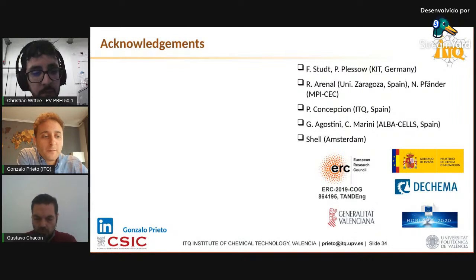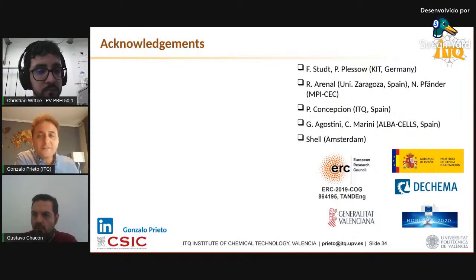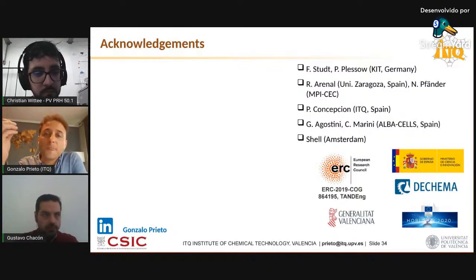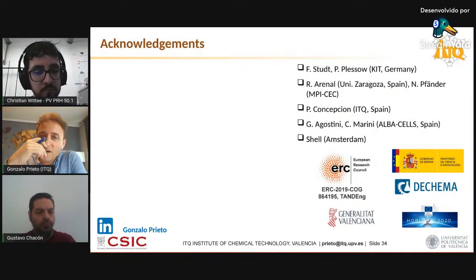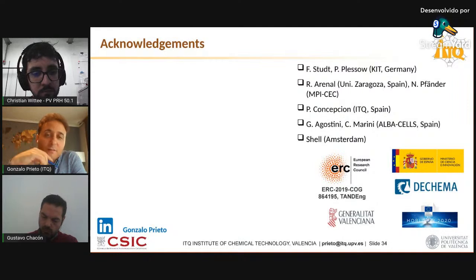Yeah, but this is also one of the powers of EXAFS compared to more local techniques such as electron microscopy, where the volume of material you may analyze is a few cubic nanometers. With EXAFS, you're going to get a full picture of how your material looks. And of course, this entails averaging the information from all different environments. Nevertheless, for a system like this with 3 square meters per gram specific surface area, exposing preferentially this 100 tin oxide facet, then you can be more or less sure that this is the facet on which the large majority of your rhodium centers are being stabilized in the real material too.